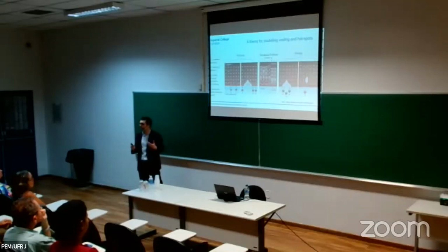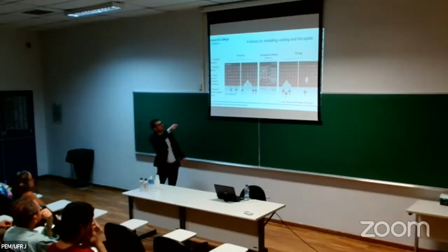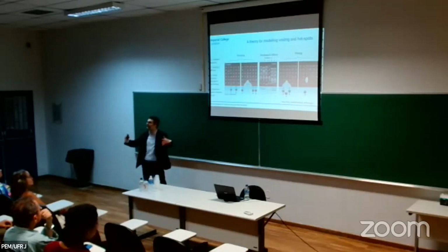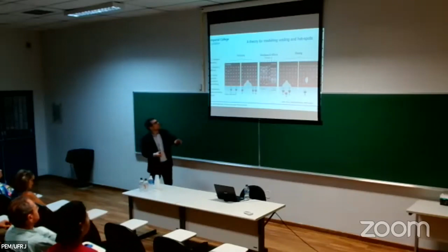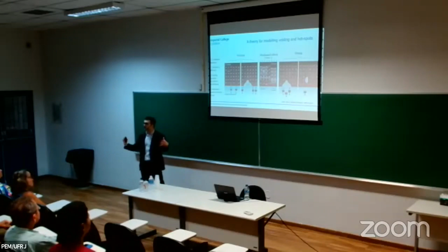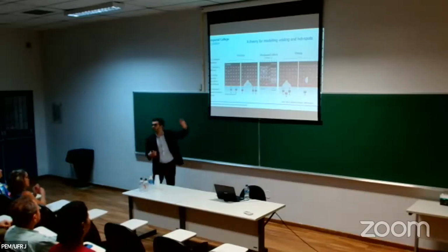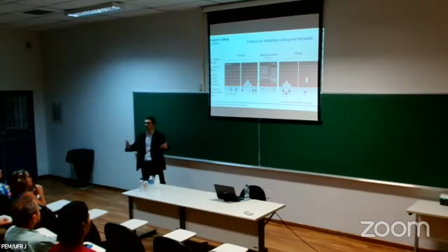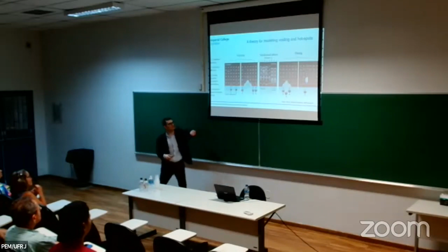You also need to capture vacancy lithium diffusion, so solid state diffusion of lithium, lithium atoms moving to the anode. This leads to some mechanical issues. So you have these chemical strains that we discussed before. You also need to capture the generation and growth of those voids. And this is basically vacancy generation or annihilation. So you need to describe the equations, the formation and the evolution of those voids. And for that, we use the phase field. And then you have a lot of mechanics in there.